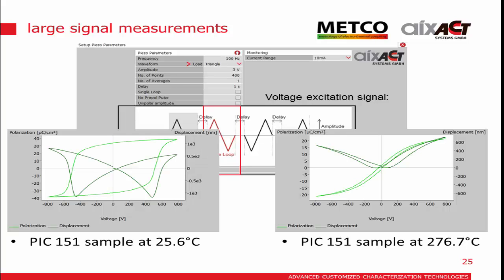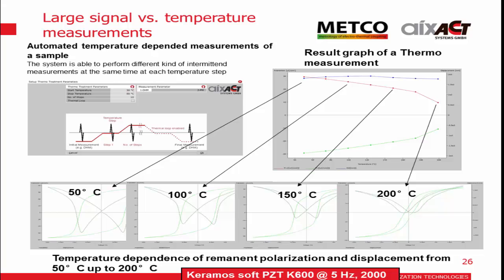And this is, for example, the difference between a room temperature and this is PZT as well at 280 degrees C. So you get, the loop gets very narrow, and you can automate this over temperature, so you can monitor the change of various parameters over temperature and define your test pattern accordingly.